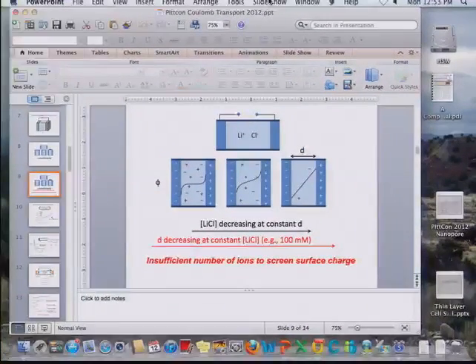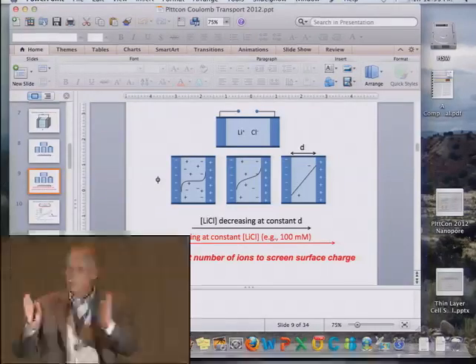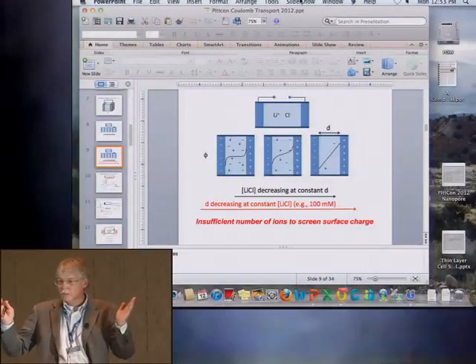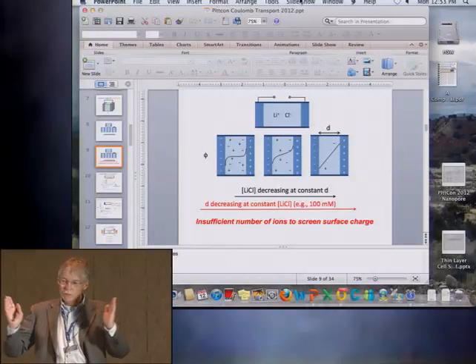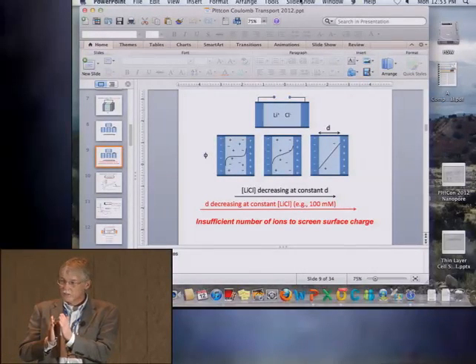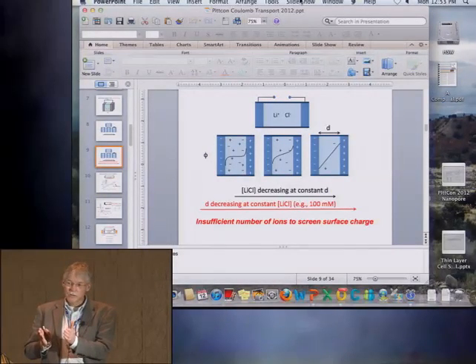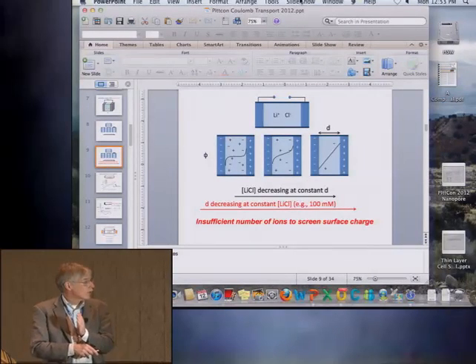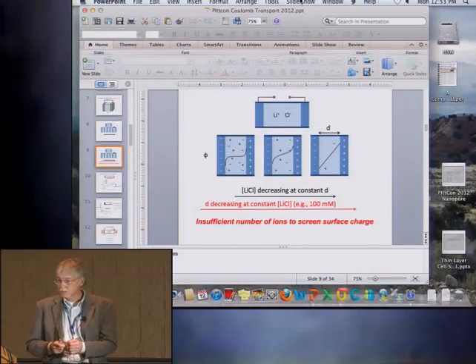What we're going to do here is keep the lithium chloride, or the electrolyte concentration, constant, and decrease the width of the cell. And if you do that, you get exactly the same pattern of electrostatic potential profiles, because if you keep the lithium chloride concentration constant, say at 100 millimolar, and you push these electrodes together, you're going to run out of ions to screen the charge on the metal surface. So even though this case corresponds to 10th molar electrolyte, you'll end up with this capacitor-like electrostatic potential.